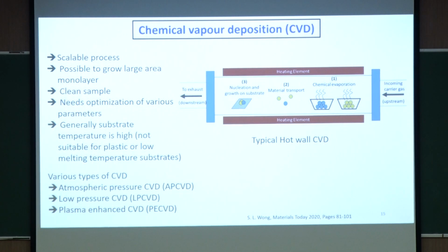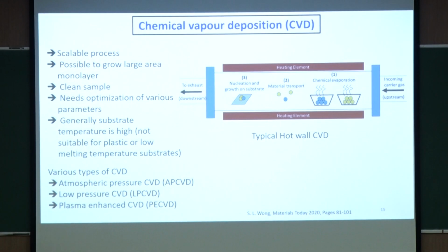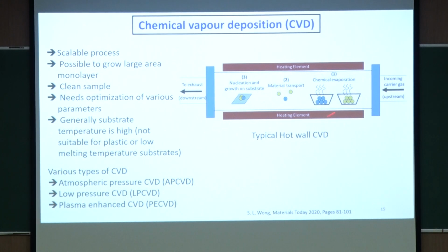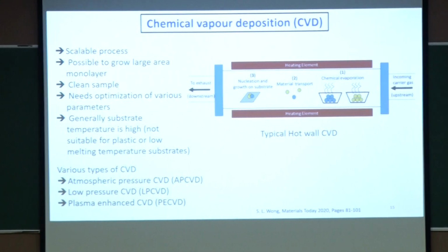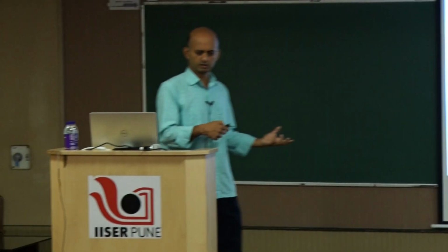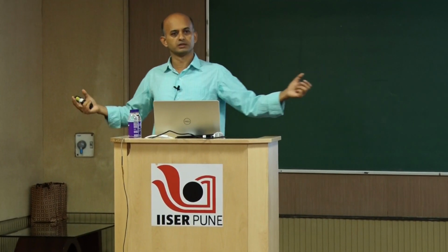But once you optimize it, generally it works. At least for graphene and other materials, people have optimized it quite well. But the problem is that generally the substrate temperature is high. What I have shown here is called hot wall chemical vapor deposition, which is the most common thing that we use in our lab. We have a furnace, we have a quartz tube inside, so you are heating that quartz tube. That's why it is called hot wall.